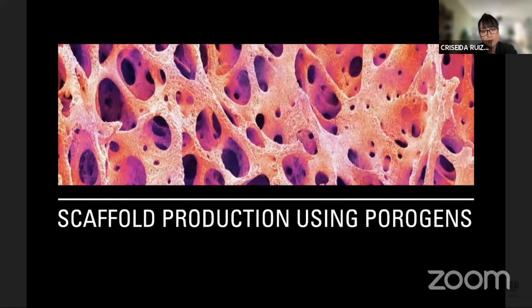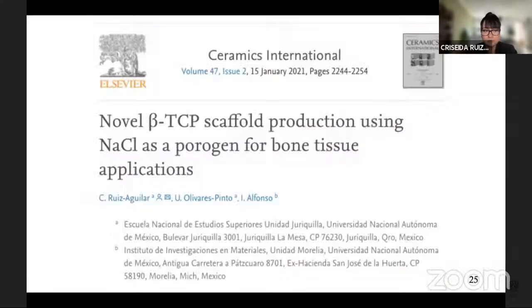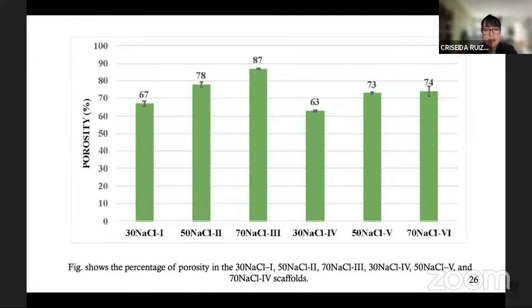Then I'm going to show scaffold production using porogens. In this study, tricalcium phosphate scaffolds were produced using a sodium chloride spacer to obtain porosity results similar to the cortical bones. The obtained values of porosity were 63% to 87%.